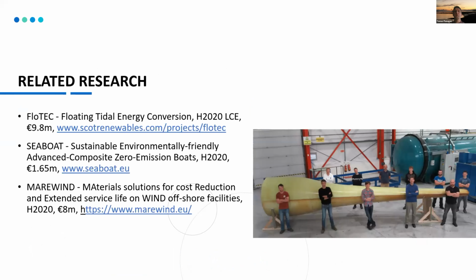Then another project was FloTEC, which I think literally ended last month. It's a 9.8 million euro project led by Orbital Marine Power. We did work to develop an 8-meter blade for the turbine using powder epoxy again, and that was tested at NUI Galway. So it was a full-scale test, and it was the largest blade to be tested in both static and fatigue. Again, we got good results, with good correlation between the computational models and the test data. And we're involved in a new project, which is MAREWIND. It's led by Luridera in Spain, and it's looking at novel materials to reduce costs and extend the life of offshore wind.